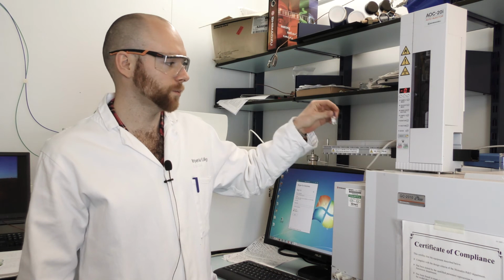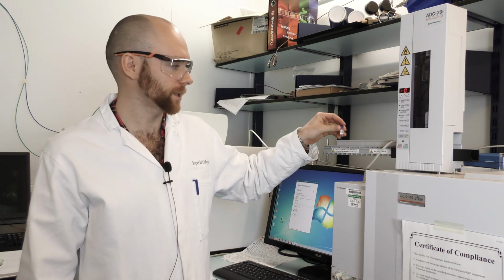Our most significant result was that the chiral separation capacity increased with the more defective frameworks. And to test this, we used a gas chromatograph fitted with a chiral column. So here's the samples we inject into the gas chromatograph, and they're separated with the chiral column, and then we get two peaks coming out.